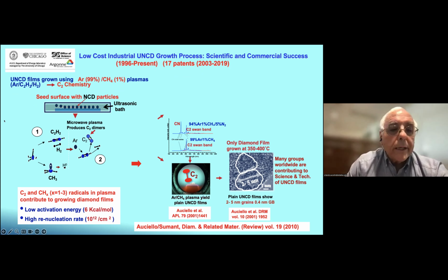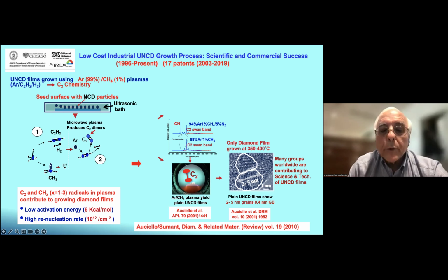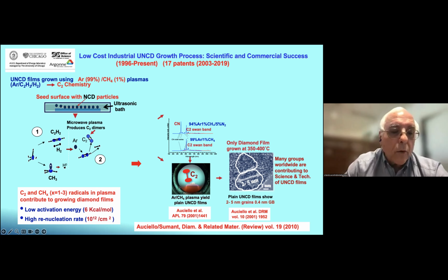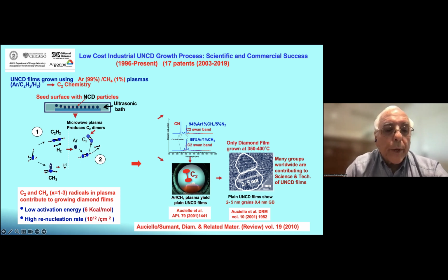What we found is that in the plasma, the green plasma we produce, the CH4 is cracked into C2H2 and argon colliding there, develop these C2 dimers that are two carbon atoms, but without hydrogen. And that's why the low activation energy in our growth film is 6 kilocalories per mole, high renucleation rate of 10 to the 12 per centimeter square. And because of this unique patented process, we are the only ones that can grow these diamond films at 350 to 400 degrees centigrade, as shown here on the right.